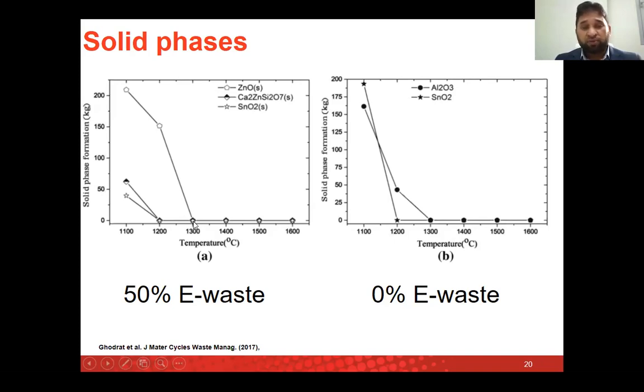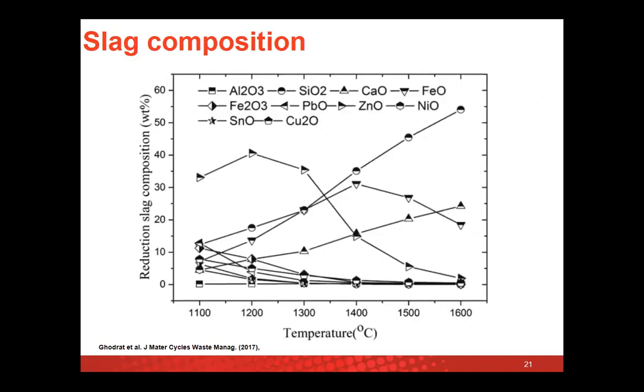You can see if you have 50% electronic waste, the minimum processing temperature is 1300 degrees centigrade, because at 1300 degrees centigrade you can bring all solids into liquid state, okay, and then it will be easy. Otherwise, when you are doing some pyrometallurgical process and you have a lot of solid phase in the form of slag or some solid phases, this will reduce the overall reaction kinetics, and the process becomes stubborn, and that is not easy to handle and monitor. Okay, so basically the challenge when you use electronic waste, of course, is the formation of the solid phases. This is another one of the challenges that you need to tackle when you're going to work in this field.